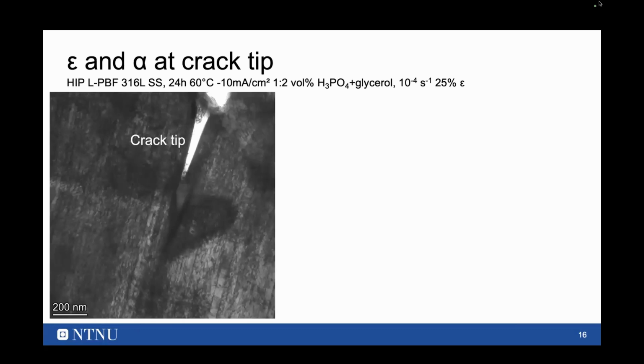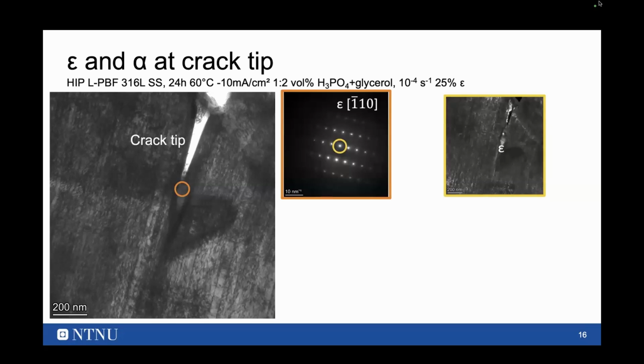We took a lamella from the fracture plane. This on top is parallel to the normal plane. This is a crack tip that was present. Around it there was all austenite, but we took a diffraction pattern right in the middle, and there we saw epsilon martensite. Taking the dark field again, we see that epsilon is actually present along the crack. So the crack is propagating along this epsilon, or epsilon is promoting the crack propagation.